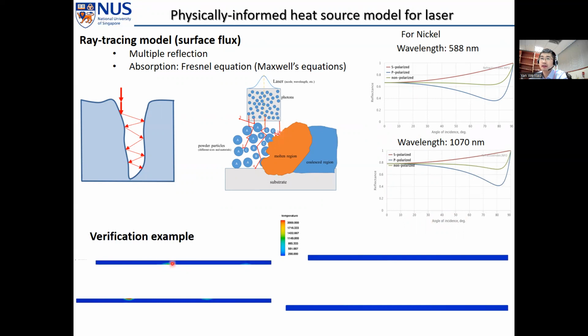And this is a verification case. We assume a laser coming from here. And you can see the simulation results like here. And you can see the trajectory of the laser is the same as expected. And also the first irradiation spot gets melted, and then the second one you can see obvious temperature rise, and the third one you can see the temperature rise but lower, and the fourth one you can barely see the temperature rise. This is due to the energy of the laser becoming lower and lower. So this demonstrates the validity of our implementation of the heat source model.